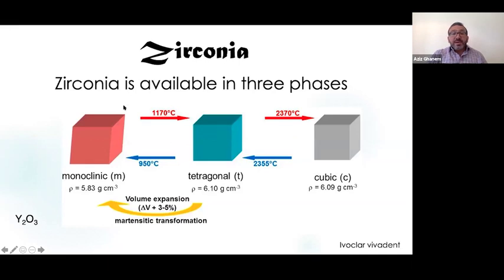Okay, so in order to stabilize the zirconia, a dopant is added to it, and the most commonly used dopant is yttrium oxide. Different dopants have been added to zirconia, such as magnesium and cerium, but the most commonly used oxide is yttrium oxide. The amount of yttrium oxide added to the zirconia by volume will determine the strength and the optical properties of the material, and also decide which phase the material is in. I'm going to talk about that later on, and the amount of yttrium is going to affect